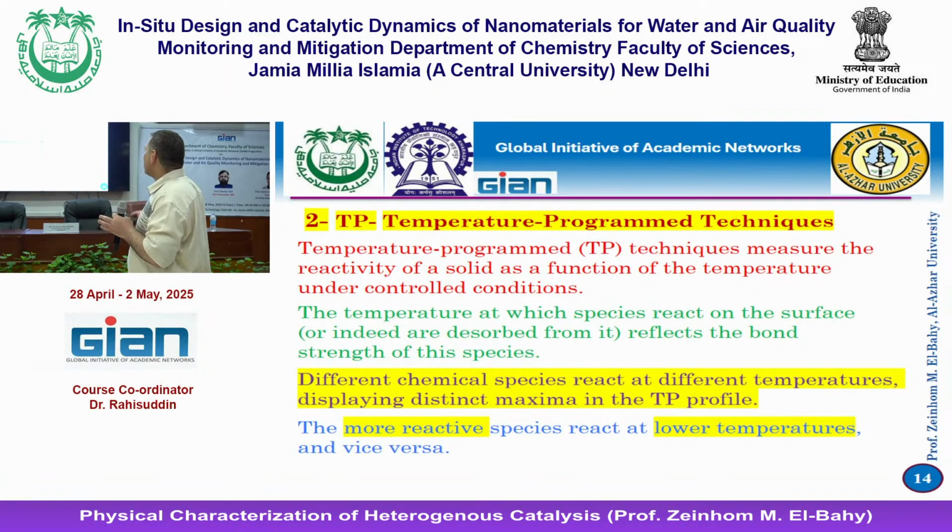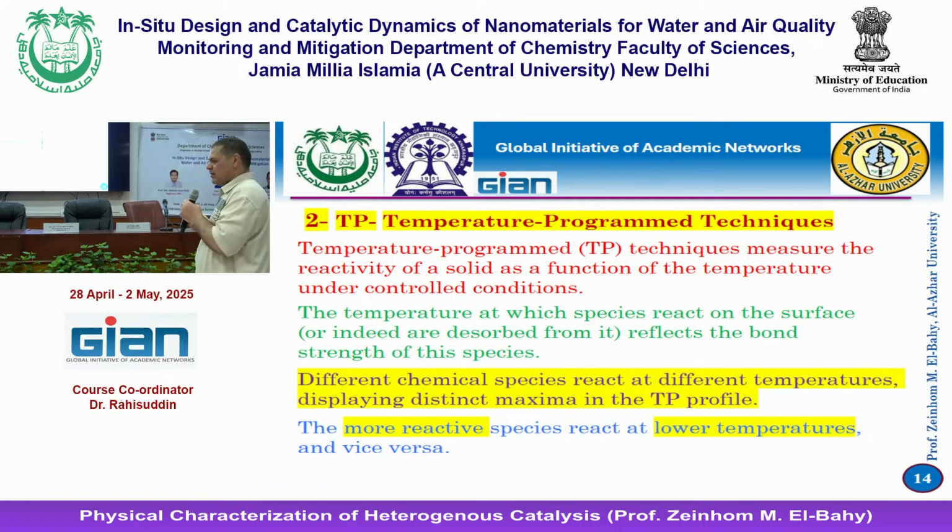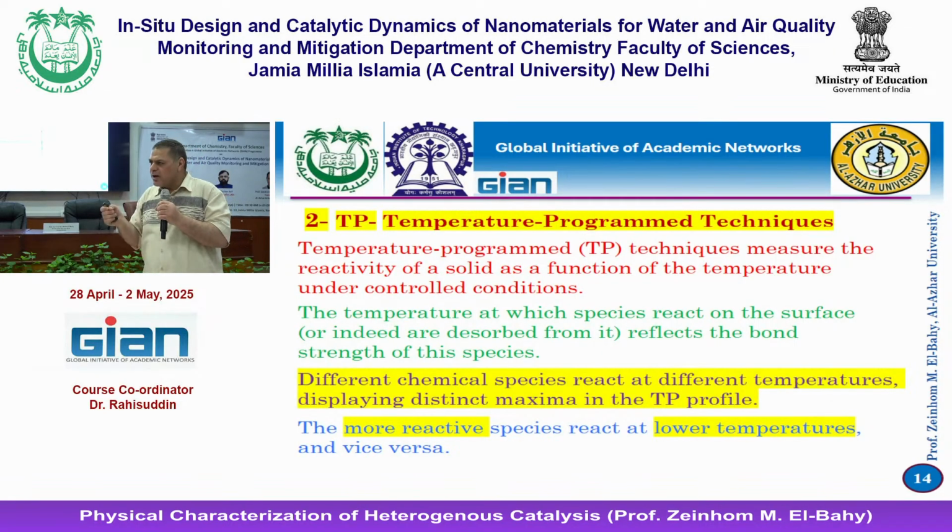This is a technique that measures the reactivity of a solid as a function of the temperature under controlled conditions, and the temperature at which species react on the surface or indeed are desorbed from it, because the temperature of adsorption or desorption determines how strong your site is, if it is a strong acidic site or strong basic or weak.